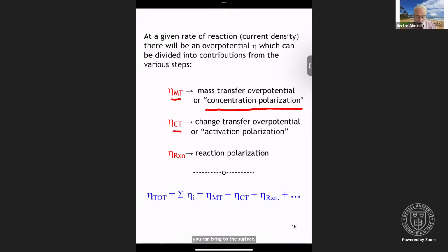You can have charge transfer overpotential or activation polarization. This means this is a regime where the rate of the electrode reaction depends on the applied potential. And we'll see later on when we discuss this in detail, if you have a process, initially you'll be limited by the kinetics of electron transfer, so-called activation polarization. In that regime, the current will be potential dependent. At some point, you overcome all barriers, and instead of activation control, you're going to be mass transport control. So there's a transition from activation control to a mixed control to mass transport control. And we'll go into those in great detail.